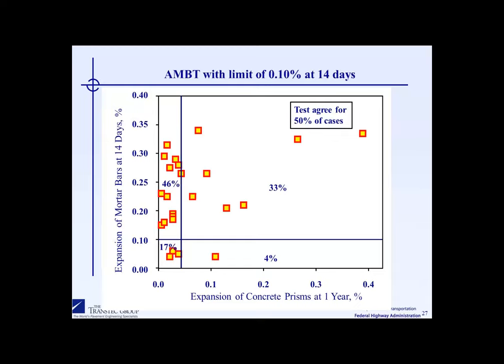Now, when we start comparing the concrete prism test to the accelerated mortar bar test, we see quite a bit of discrepancy between the two tests. This data set shows that we only get agreement between the two tests in about half the cases. Generally speaking, we tend to rely on the concrete prism test as the best indicator of reactivity. So this slide is suggesting that the accelerated mortar bar test will give us the wrong answer about half the time when the test is run for 14 days.